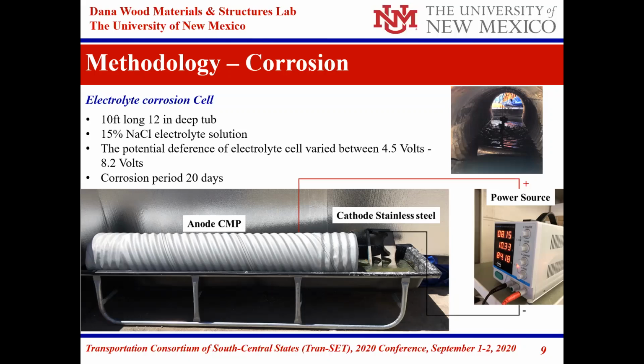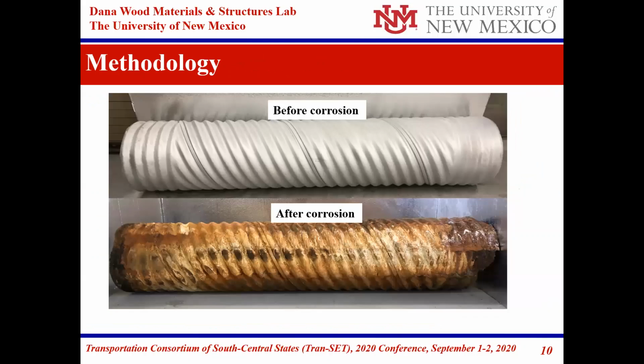So this is the pipe shape, and one of the things we've done, by the way, is first we eliminated the galvanization, because usually on these metal pipes there is a layer of galvanization on top to protect the pipe, despite the fact that it doesn't work perfectly. But we have to remove it before, and that's the sandblasting you see before corrosion, and then you see the corrosion after at the bottom. And this is the corrosion after 20 days in our accelerated corrosion cell.